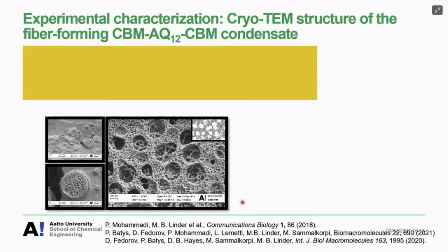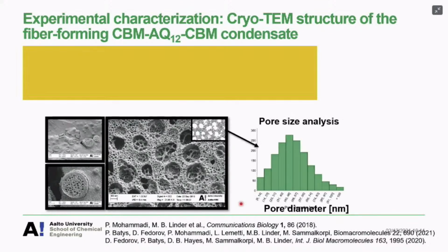Okay, so the starting point for the modeling. This is a cryo-TEM high-resolution image of this fiber-forming silk-like protein condensate. So this is the condensate droplet imaged by cryo-TEM. If one analyzes the pore sizes there, it's forming a porous structure that has bigger pores, smaller pores, and it looks like a sponge. The pore sizes have a quite well-defined distribution.